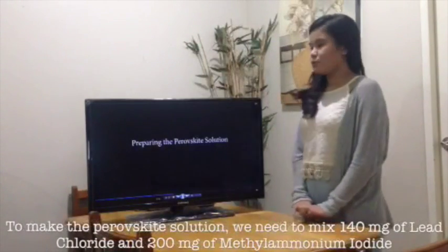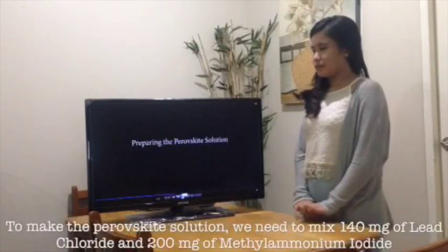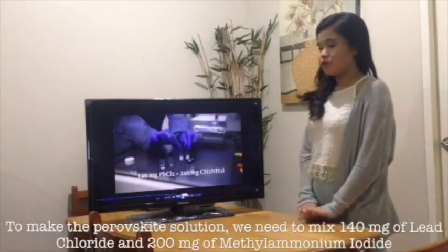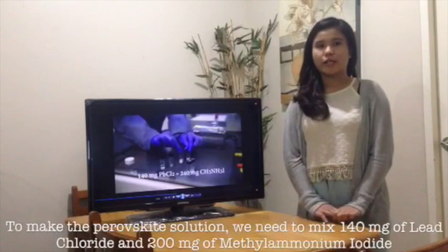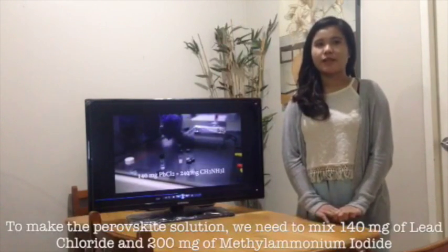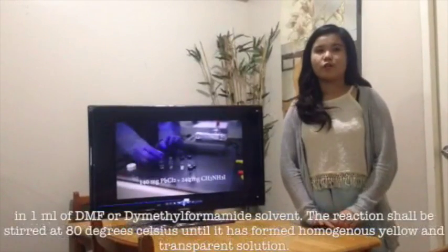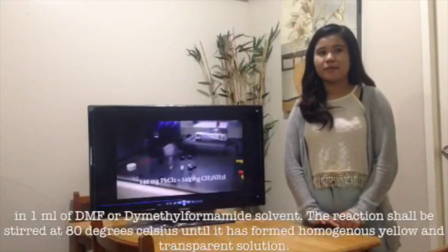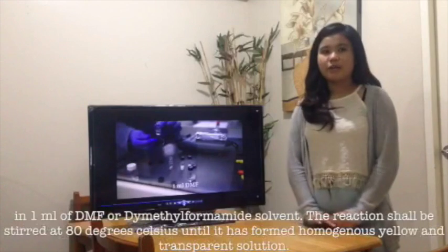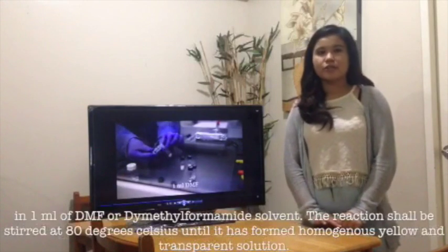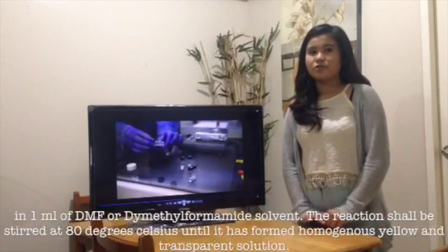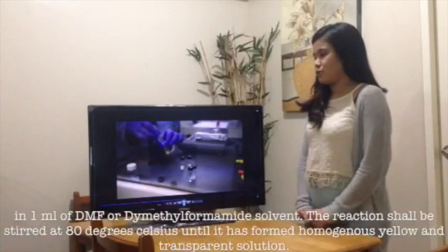To make the perovskite solution, we need to mix 140 mg of lead chloride and 200 mg of methylammonium iodide in 1 ml of DMF or dimethylformamide solvent. The reaction shall be stirred at 80 Celsius until it has formed a homogeneous yellow and transparent solution.